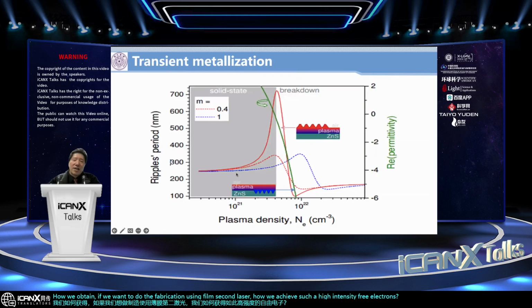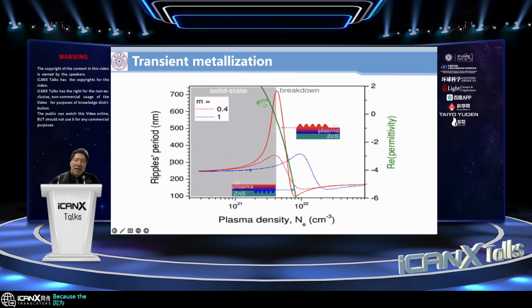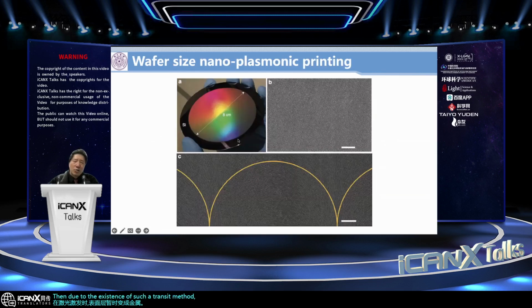The answer is femtosecond laser high excitation. Because the intensity of the light is very strong, the transient high excitation can produce a very high density of transient electrons. It means any material, even if it is a dielectric, upon the laser excitation transiently the surface layer becomes metal. Due to the existence of such a transient metal layer, we can couple the laser into the surface and convert the light wave to the SPP wave.